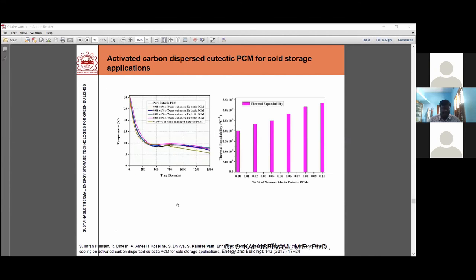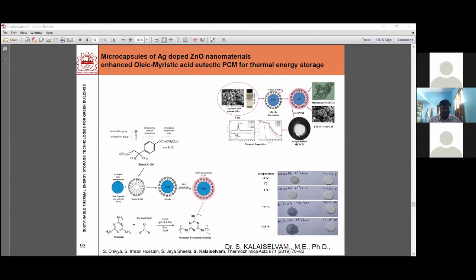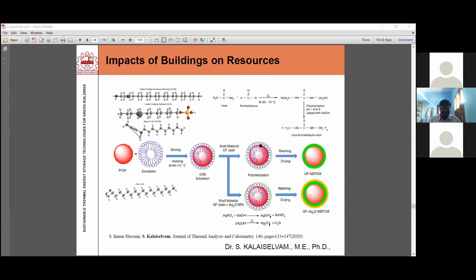So here, if you take this at high temperature, this is a eutectic picture. This is a micro-encapsulated PCM. It's in solid state. This eutectic mixture at 0 degrees centigrade is solid. At plus 5 degrees centigrade, it started melting, but the micro-encapsulated PCM is still in the same state. At plus 25, it becomes fully liquid. The state has not changed, but latent heat storage takes place. And this is again a micro-encapsulated PCM.